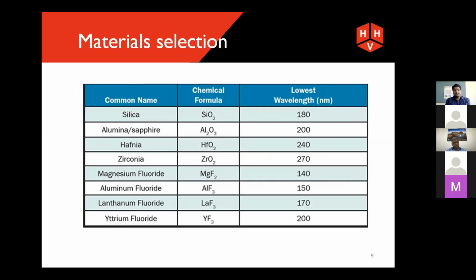For doing this kind of dichroic coating, we need to select the raw materials. The raw materials are the glass and aluminum, and for the coating materials, we have a limited set which can work in the UV region. For example, silica, alumina, hafnia, zirconia, and many other fluorides. We need for the interference effect a high index and a low index layer combination, as I explained in my earlier slide. In this list, hafnia and zirconia are the high index layers, alumina is the medium index, and all the remaining layers are low index layers.